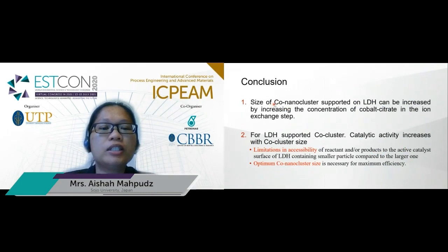So as a conclusion, the size of the cobalt nanocluster supported on LDH can be increased by increasing the concentration of cobalt citrate in the ion exchange step. And secondly, for LDH supported cobalt clusters, catalytic activity increases with cobalt cluster size, and is mainly limited by accessibility, as well as probably there is an optimum cobalt nanocluster size that is necessary for maximum efficiency. Thank you.